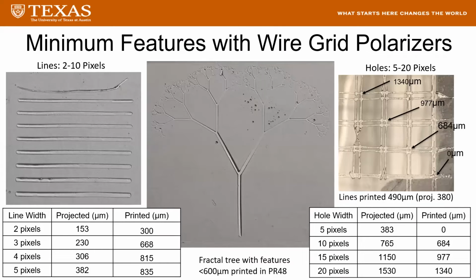So these features were cured with an LCD that had the film polarizer proximal to the light source replaced with a wire grid polarizer. This LCD had 75 micron pixels, and we were curing PR48, a relatively easy to cure acrylate resin. And we were curing lines ranging from 2 to 10 pixels and holes 5 to 20 pixels. The smallest lines and holes we were able to resolve were 300 and 680 microns respectively.